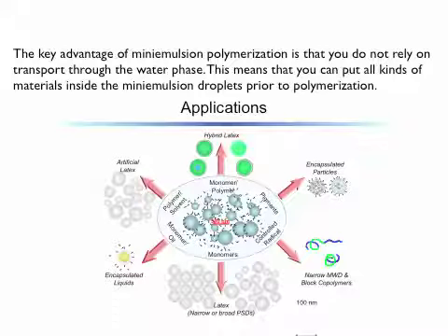Sometimes people that want to do organic chemistry want to react one component that's quite hydrophilic and the other half is very hydrophobic, and they don't really know how to mix these two. You can just make a mini emulsion of one, and the other one is in the continuous phase, and the surface area is massive, so the concentration locally is very high, so you get a very fast reaction. The only downside is you have to get rid of the surfactant, but that's only 1 or 2 weight%, and typically in organic chemistry you have all kinds of side reactions, so to get rid of that is not that difficult.